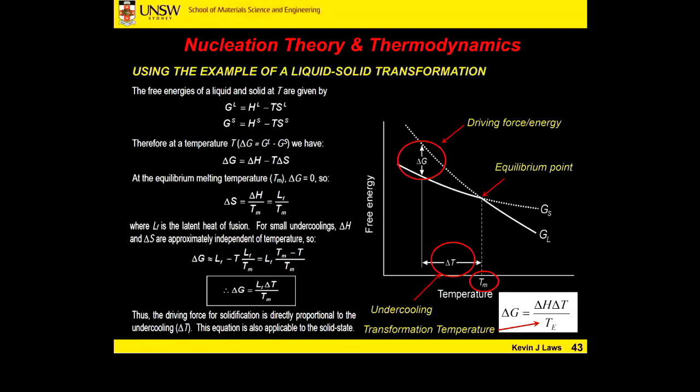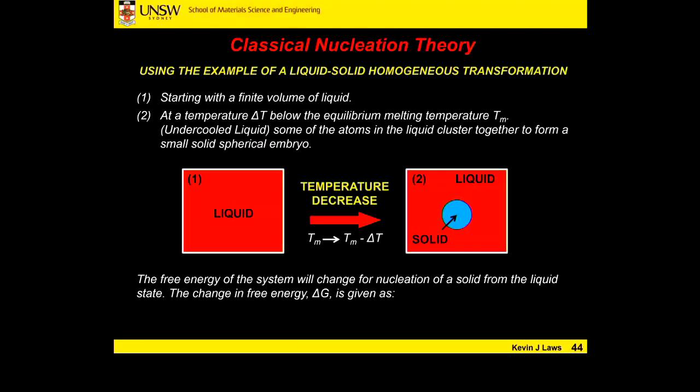We get onto some of the metallic glass stuff a little bit down the track, where we actually find that the free energy between the liquid and the solid are incredibly close together. And this is a chemical thing and a diffusion-based process thing as well. When delta G is very, very small, it's very easy to undercool much, much further. But we'll get onto that later. Is everybody clear? And we'll go on to the next one, because it's more equations and stuff.